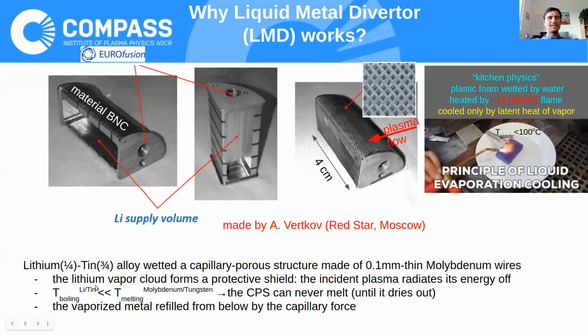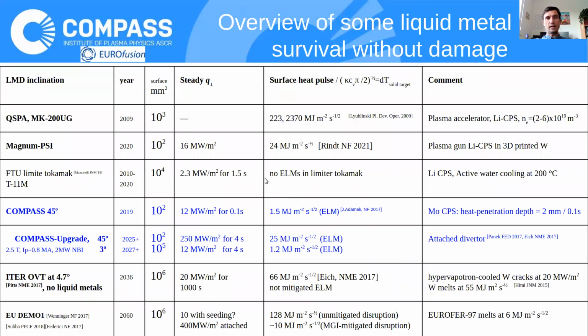And of course, the chosen liquid must have a boiling temperature lower, or much lower, than the melting temperature of the molybdenum or tungsten wires used. And the vaporized matter is then refilled to the surface by capillary forces. So that's why we have this lithium supply volume, a kind of reservoir, and then through these channels by capillary forces, it just refills back to the surface. And we have demonstrated that it can be done pretty easily even during the ELM rise time and decay time.